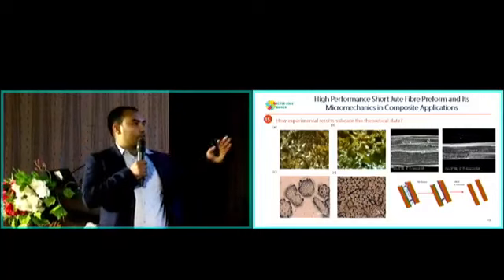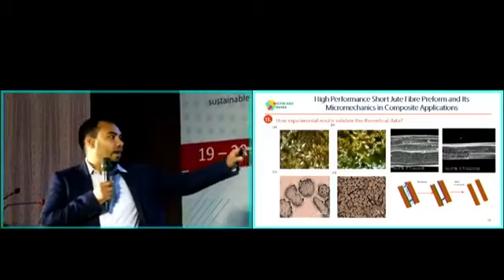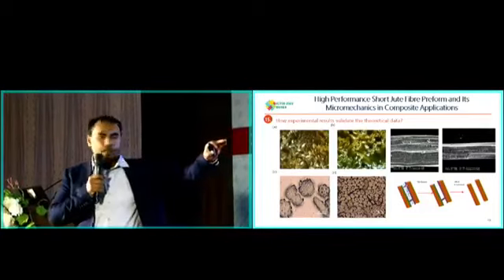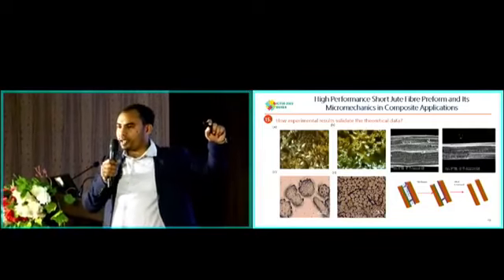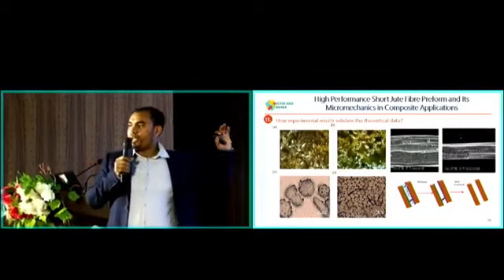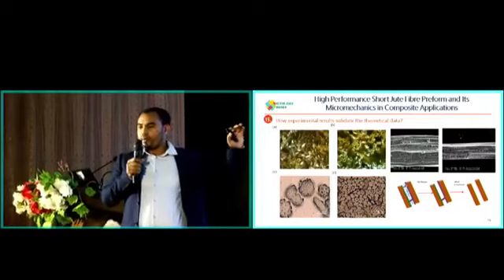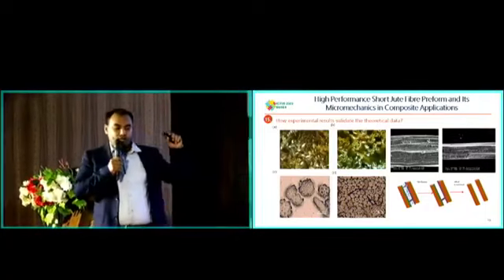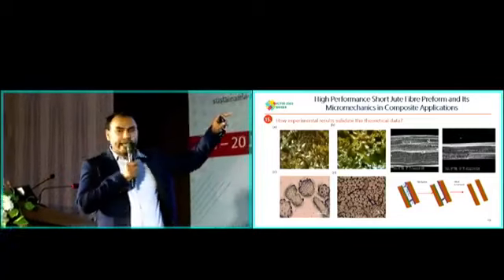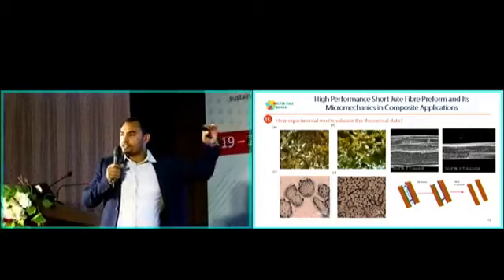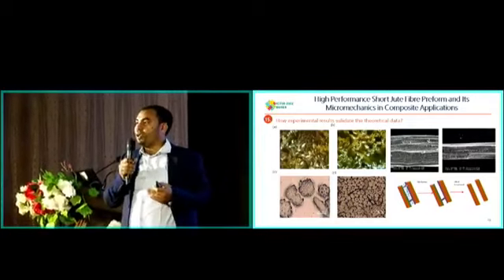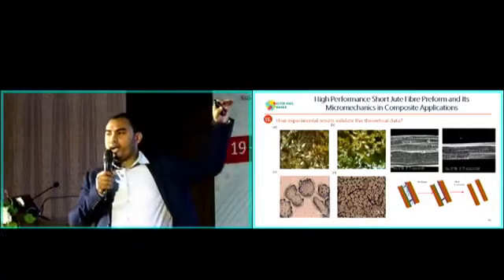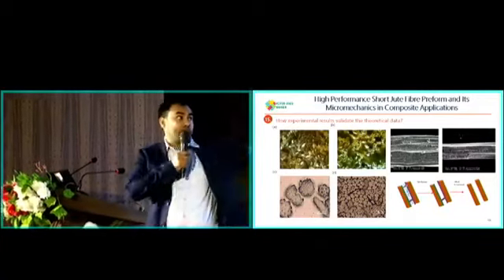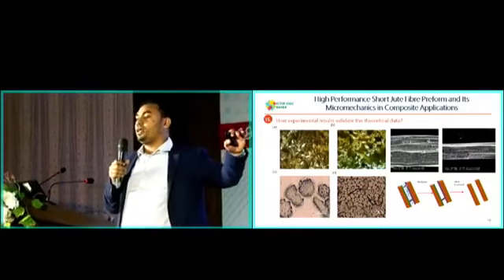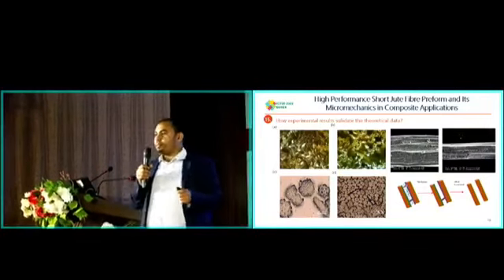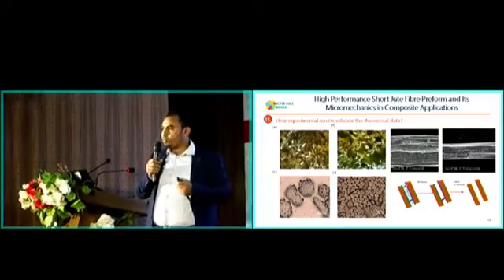And you also see, after fibrillation and mechanical extraction, how the fiber breaks, and eventually how uniform the fiber will look like. So that means we have successfully claimed and also confirmed how a raw fiber can be used for producing high performance jute fiber architecture for composite application. And clearly from the SEM image, you can see the raw fibers, because of the presence of a lot of polysaccharides or impurities, the diameter is very high, whereas after the alkaline treatment and extraction process, the diameter is reduced and the uniformity of the fibers is improved. Therefore, we can claim that the fiber used in the study has achieved maximum mechanical properties.